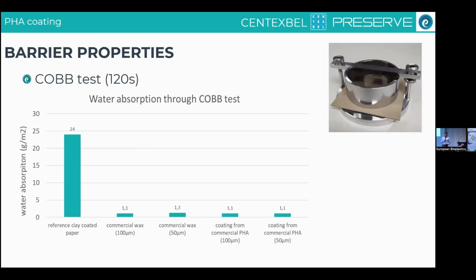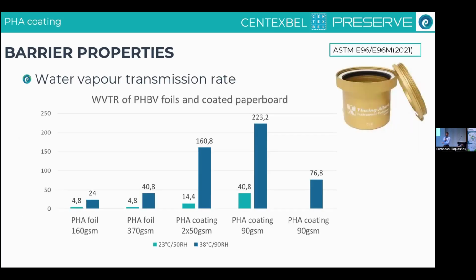Then for the barrier properties, one of the properties we started measuring is the COBB test. This determines in what way water gets absorbed into the paperboard. So the less water absorbed, the better. We see that the reference paperboard on the left absorbs about 25 grams of water per square meter in 2 minutes, while for our PHA coatings we are at a value of about 1.1 grams, which is actually quite similar to some commercial wax-based solutions that can already be used for these kinds of packaging materials.